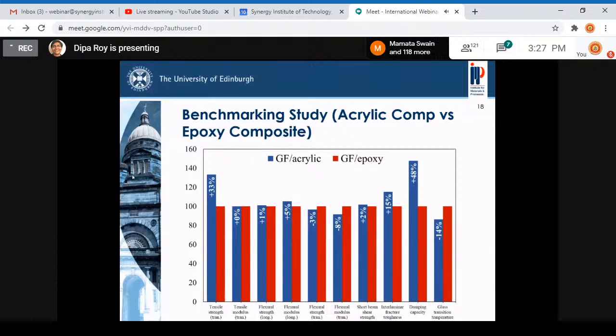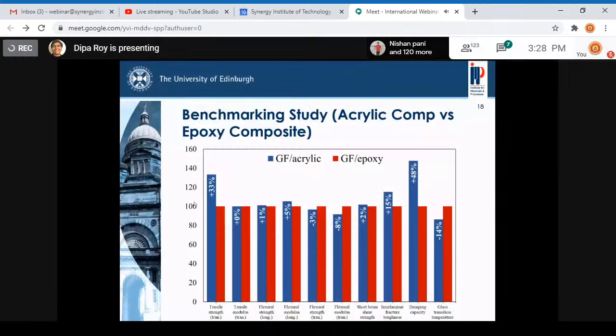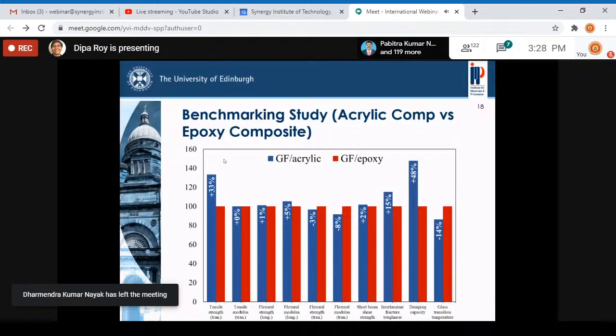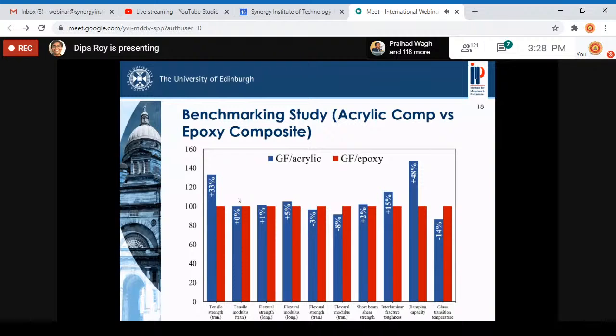When we compared the mechanical properties, tensile strength both longitudinal and transverse, interlaminar properties, damping capacity, everything between the acrylic composite and the epoxy composite, they are pretty much at par, quite close. The only difference was that the transverse tensile property for the acrylic composite was about 33% higher, which was quite significant. Damping capacity was higher as well, as we discussed in our previous slide. But the transverse tensile property is dominated by the matrix behavior. So clearly this result showed that the acrylic matrix was performing quite well in the transverse direction. This was a very good observation, and we are very happy to see this result.